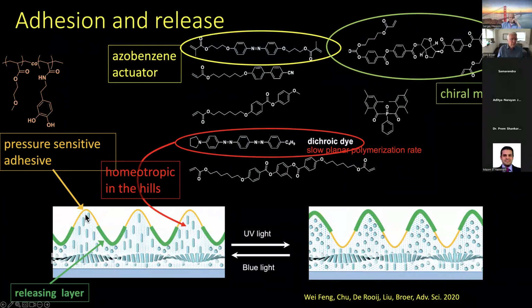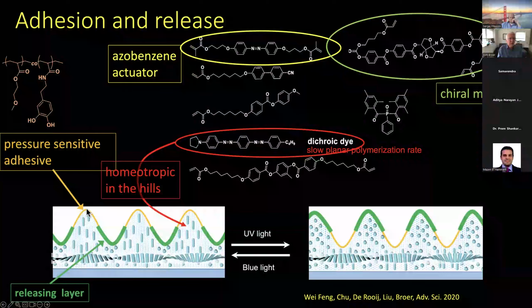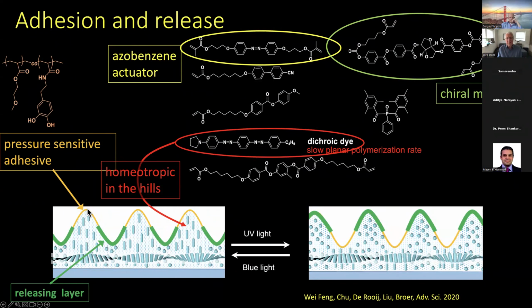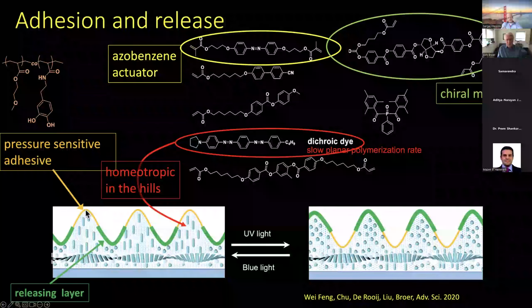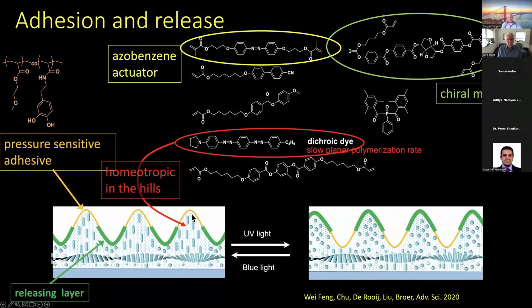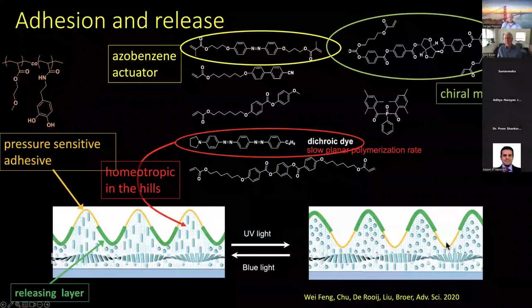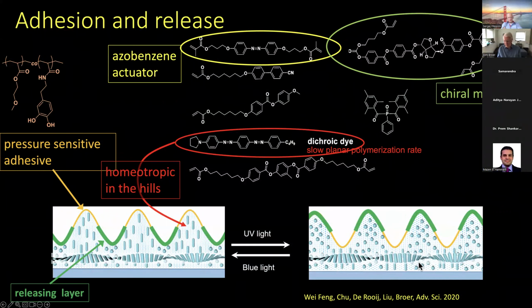Now if you apply a pressure sensitive adhesive at the top of the films and a releasing layer in the valleys, you can actually switch it from a system where the surface is mainly adhesive because of the pressure sensitive adhesive to a surface which is mainly releasing because we are just hiding the pressure sensitive adhesive in the valleys.